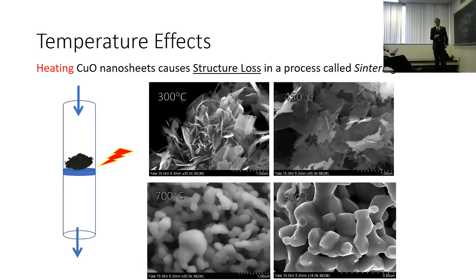These are nanosheets heated to 300, and they look very similar to nanosheets unheated. Heating to 300 doesn't really do anything. Heating to 450 Celsius does do something. You start to get rounding of the edges, and you start to lose your structure. At 700, your structure's gone. At 900, you get this other weird bulk material going on. This is nothing new, people knew about this for ages. It's called sintering. When you heat nanomaterials up, you lose structure. But I saw it with my own eyes, and I thought that was pretty cool.